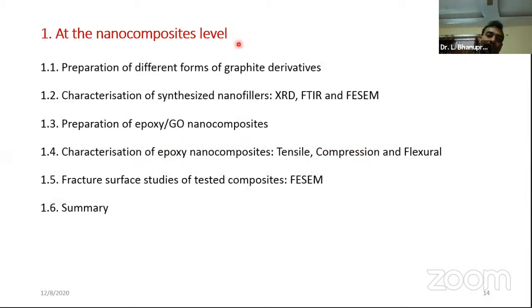At the nanocomposite level, we first prepared different forms of graphite derivatives, as I mentioned: the oxide form, exfoliated form, and then the reduced form. We prepared them at the lab level; we haven't directly purchased them. Then we characterized them at each stage, to confirm the oxidation reaction, the exfoliation process, and the reduction process. We characterized the nanofillers using XRD, X-ray diffraction, FTIR, Fourier transform infrared spectroscopy, and FESEM, field emission scanning electron microscopic images. From these three techniques, we confirmed the oxidation followed by the exfoliation and reduction processes.